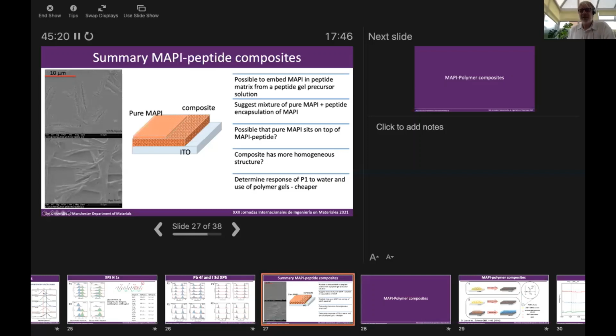So the next steps here are really to determine the response, as I said, of this peptide to water, to see whether we do see any changes in the protonation of the amine groups in the peptide when it's exposed to water. And that will potentially allow us to postulate a mechanism as to how the protection occurs. Obviously, these peptides will swell in water because that's what they're used for in cell culture applications. They use water to swell the gel and then grow cells on them. And so they're not keeping water out, but it may be that they prevent the water from actually reacting with the MAPI in these materials.